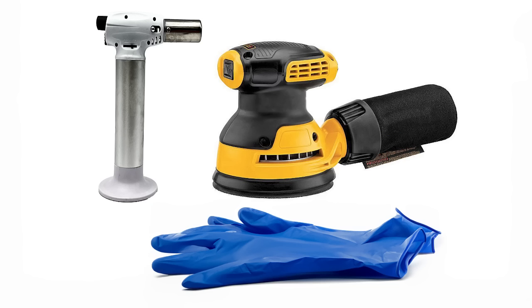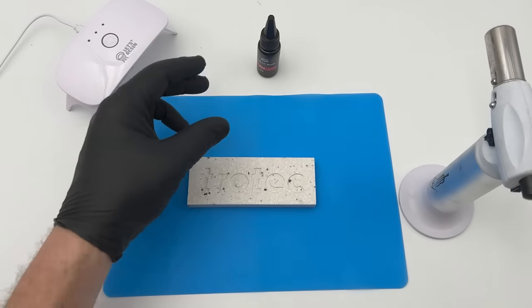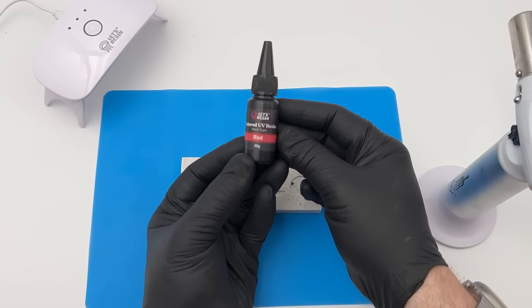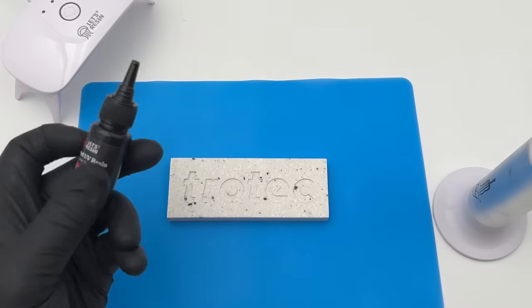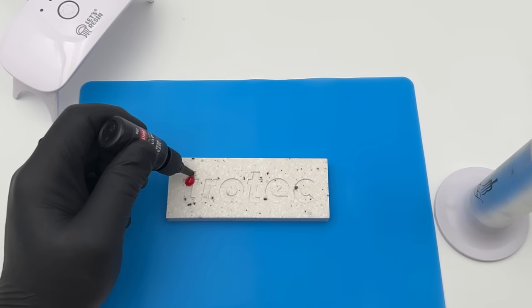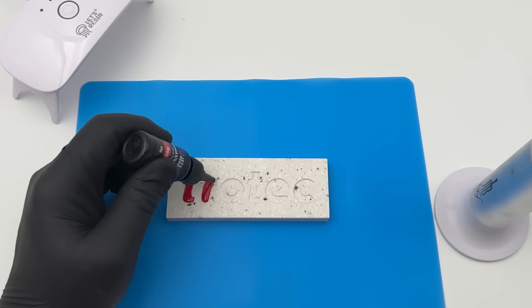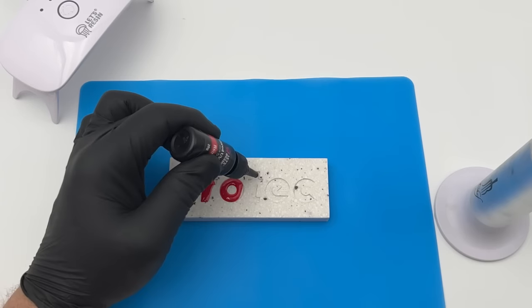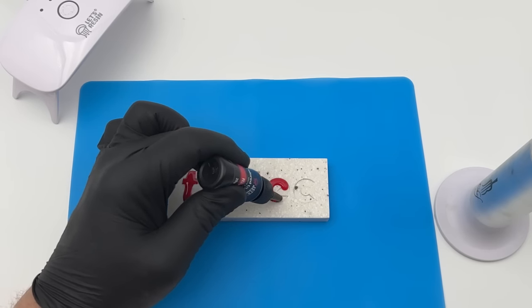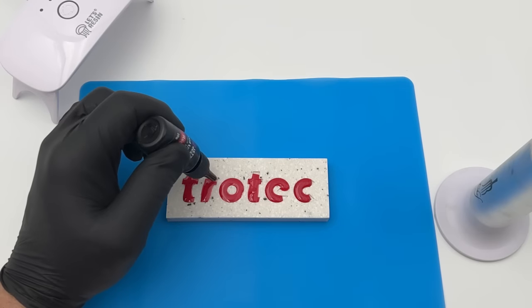In addition to this kit, a small butane torch or heat gun, rubber gloves, and a sander will also be necessary. Gather these supplies and place the engraving onto the silicone mat provided in this starter kit. Cured epoxy will not stick to this mat. For this example, I will use red epoxy. As you pour the epoxy, you will see that it will slowly self-level into the engrave channels, making sure to place more than you think you will need, as it will shrink a bit when cured.